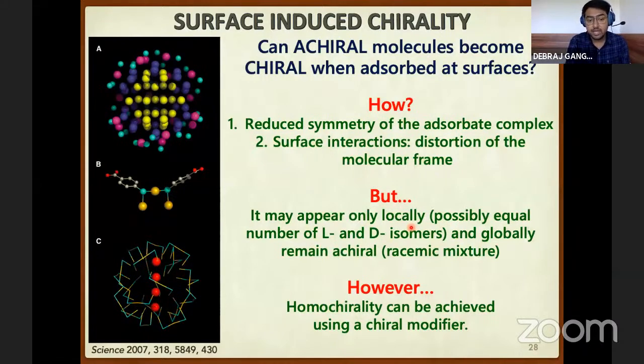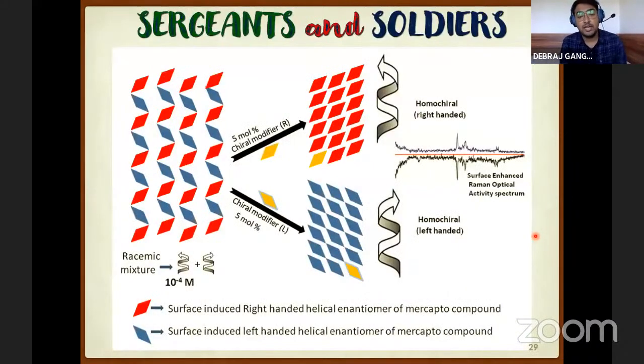Local, I mean that it may give rise to some L isomers and some D isomers, and globally the entire mixture may remain achiral. So we may have an equal number of L and D isomers, and it will be impossible to detect in surface enhanced Raman optical activity. However, homochirality can be achieved using a chiral modifier, which I will show. A chiral modifier can induce homochirality in a racemic mixture, or in an achiral solution which has an equal number of right and left-handed isomers. So if we have a racemic mixture with an equal number of right and left-handed isomers, and we put a very small amount of a chiral modifier or a chiral molecule in it, suppose 5 mole% of a chiral modifier in it.